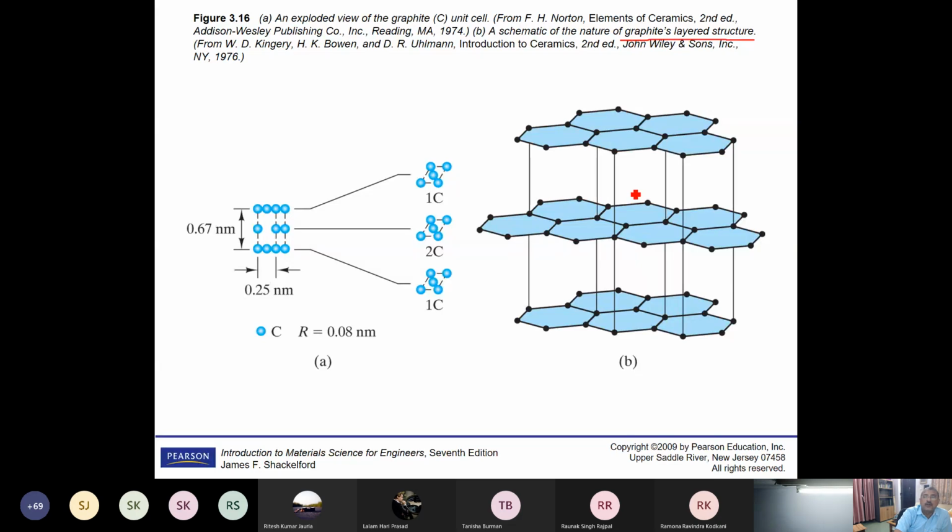The so-called anode or the negative electrode of a lithium-ion battery, which I showed you, the anode and cathode material and the electrolyte, in the introductory classes. The lithium ion during charging diffuses inside these layers of carbon, and during discharging the lithium ions come out. This is how you store charge in the graphite anode or negative electrode of a lithium-ion battery.